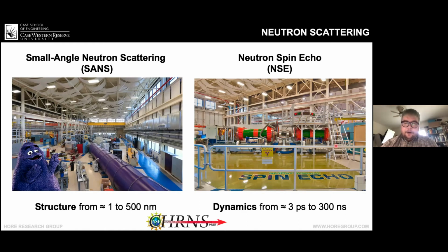This instrument here is the neutron spin echo instrument, which is analogous to NMR, but using neutrons instead. You can see by the ladder here and by the size of this pump here, these are gigantic instruments. And this spin echo instrument will measure the dynamics or the relaxation times of polymers from about 3 picoseconds to 300 nanoseconds. It has the largest time range of any neutron spectrometer.